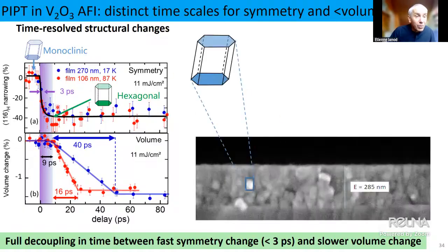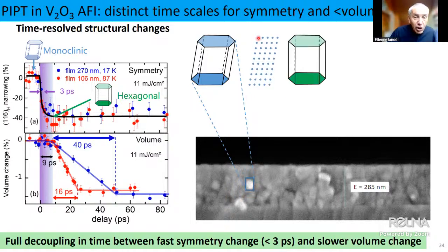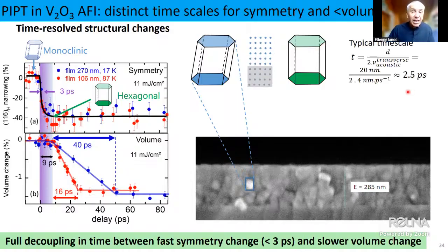In fact, what we propose is that within each ferroelastic domain, we have a propagation of a shear strain wave, that behaves as in this small animation, and that allows the system to go from distorted monoclinic to hexagonal. And if we calculate the time scale that we expect in such a scenario, we just have to divide the typical size by the propagation speed of transverse acoustic phonons, and we end up with 2 or 3 picoseconds, exactly the value we have experimentally.